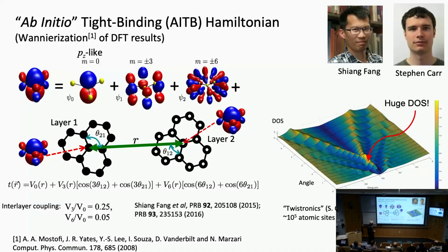As we talked, graphene is a semi-metal, zero density of states at the Fermi level. But if you go to around 1 degree of twist or so, the density of states shoots up, huge density of states here for this twist, and you see the effects that MacDonald's very simple model was also predicting. So this is from our calculations, which involved all the way up to, I think, about 50,000 atoms at that time, with this simple model, tight binding Hamiltonian, derived from the ab initio calculations that I was mentioning earlier, based on the configuration space approach.